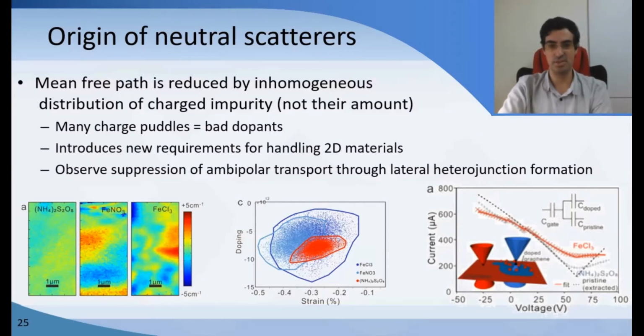And so we find that it's affecting the transconductance more significantly close to the Dirac point, and even worse, because the charge puddles are mainly one type in a uniform matrix of another. So we think that this is heavily p-type doped puddles in lightly p-type doped graphene. We find that they would more significantly affect electrons than holes. And so we're seeing this unipolar transport instead of the ambipolar transport that you would see in other etchants. So that's a bad thing, that adsorbates basically are forming these clusters on 2D materials.